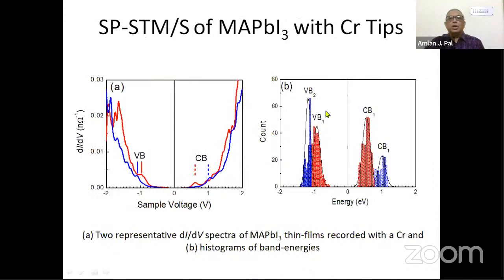Now the interesting part is what happens if I use a ferromagnetic tip, that is, if I now inject only one type of electrons. Then I find that I get two types of density of states. Either I get these two levels, or I see the levels away from them, something like this. So at some points I see only these two levels which are closer to the Fermi energy, the conduction band and the valence band, or I see the bands which are away from the Fermi energy.